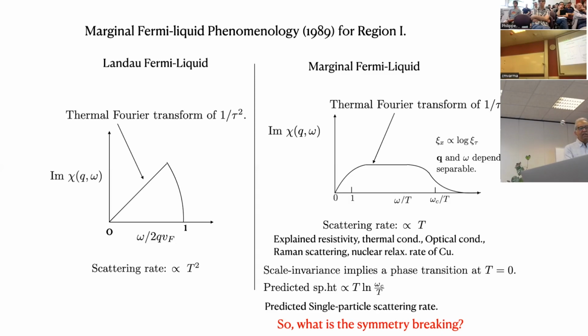And this spectrum is very unusual. You're not going to get this spectrum out of any of the extensions of the usual theory of phase transition, Wilson, Fisher, Landau, Ginzburg, etc., taken to the quantum regime. They will give you a fluctuation spectra which goes on peaking near omega going to 0 as you approach the critical point. Here, all that is happening is that this edge is moving while the bulk of the spectrum remains the same. So this is a very, very curious and different kind of criticality.